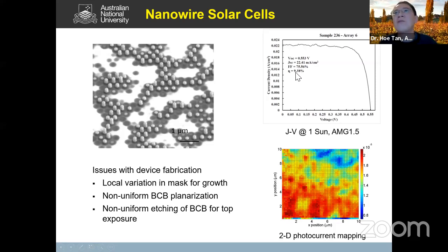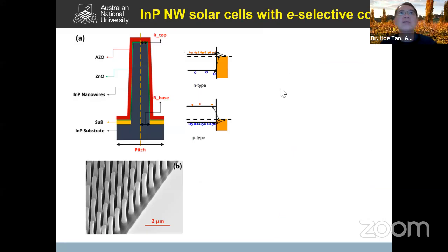One of the problems we found out is that, you see, when we planarize it and start to etch it down, not all the nanowires are exposed. You see some of the parts here don't expose. If they don't expose, you cannot make contact. And if you cannot make contact, then you get no photocurrent. Okay. So one of the problems is uniformity in terms of processing and also some local variation. When we grow the nanowire, some are taller, some are shorter. So, you know, the efficiency is not great. Okay? So, but once we know the problem, we can use other ways to do it.